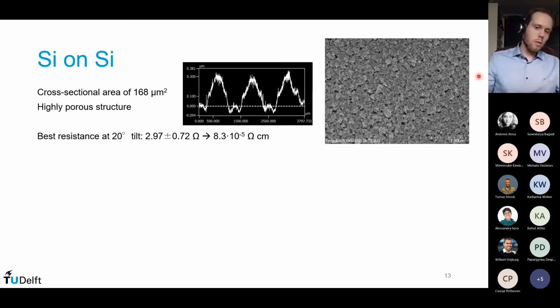It's porous up to the nanoscale because the particles are somewhere between 5 and 20 nanometers. And that means that is also a problem for the electrical performance. If you can imagine, a bulk gold line has a conductivity of, I believe, 2.2 times 10 to the minus 6 ohm centimeters, which is roughly 35 times better than the lines that we've printed here, even though these are also pure gold. And this is most likely due to the porosity, because if you have not bulk gold, but a lot of essential air gaps inside your sample, this will reduce the performance, of course.